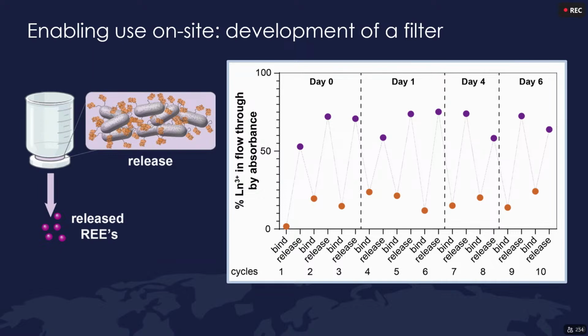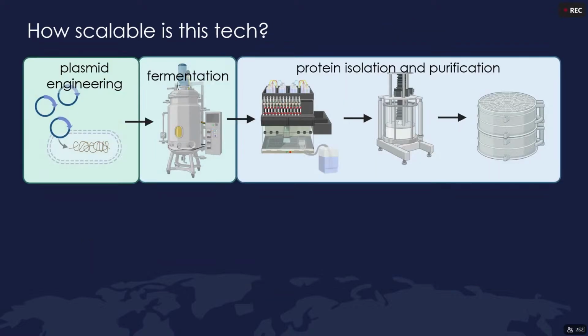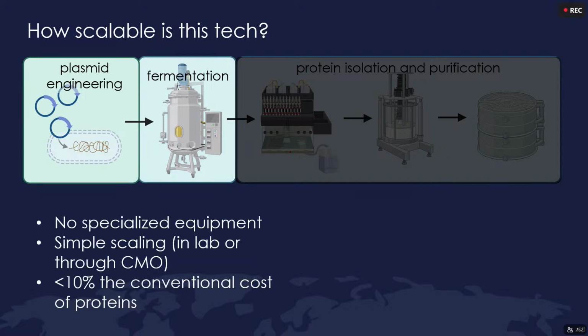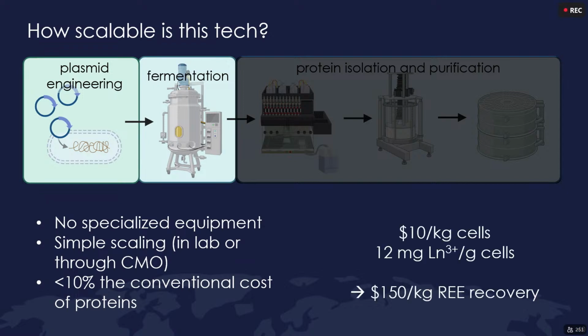But the impressive thing is that these proteins remain stable without refrigeration, just on a benchtop, even exposed to acid. And so when we think about the scalability of this tech, we now have removed all the need for downstream processing in order to use proteins, right? So we don't need any special equipment to make these protein materials, and it's less than 10% of the cost of conventional proteins. And so what this means for rare earth element recovery specifically is it costs us about $10 a kilogram to make these dried cells.